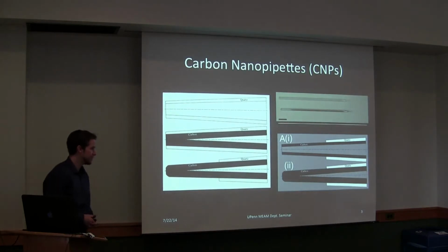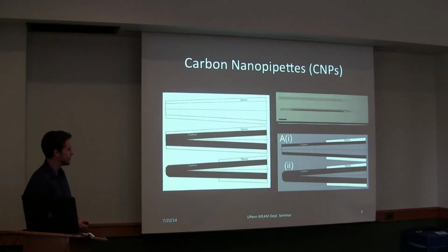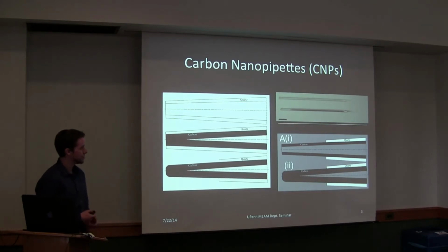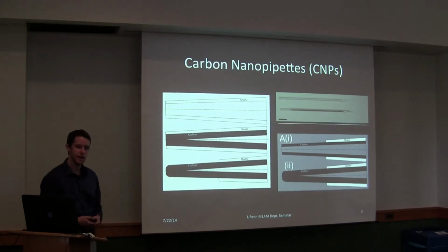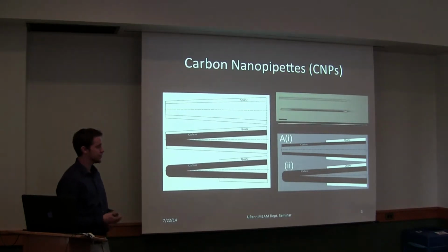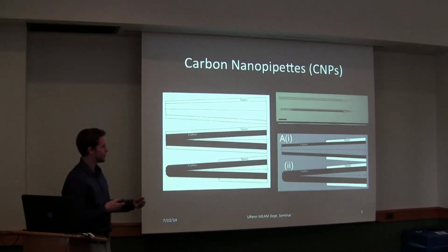So the tool that is the basis of all this work is the carbon nanopipette. It was developed in our lab a few years ago. The carbon nanopipette starts out as a pulled glass capillary. We take a glass capillary, shine a laser on it to heat it up to a high temperature, and then we apply a tension to pull it down to a very small size.